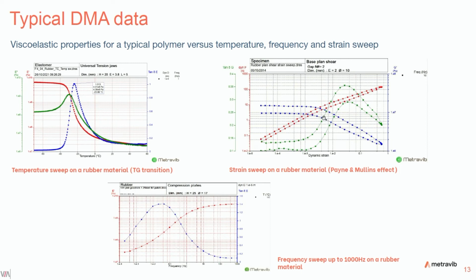Another, more important measurement is the strain sweep. You have an example on a rubber material in order to characterize the Payne effect, that is to say the linear behavior and the non-linear behavior of your material. And if you want to go back, you can characterize the Mullins effect and its strong effect on the viscoelastic properties, especially on the damping properties. And the last one, frequency sweep, just the behavior of your material as a function of the frequency. From very low frequency, up to 1000 Hz in option on the DMA Plus series instruments.